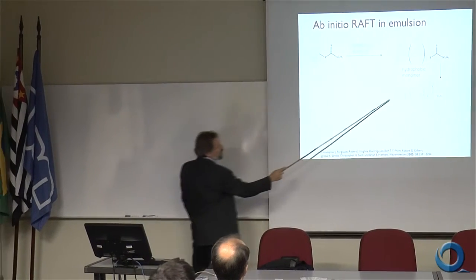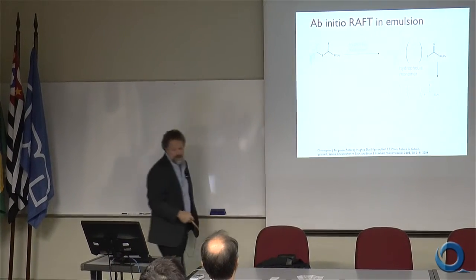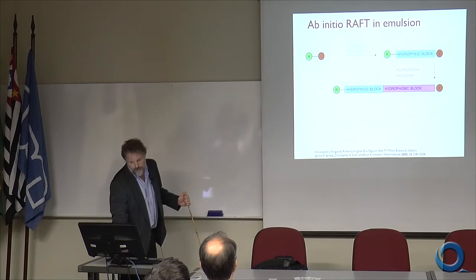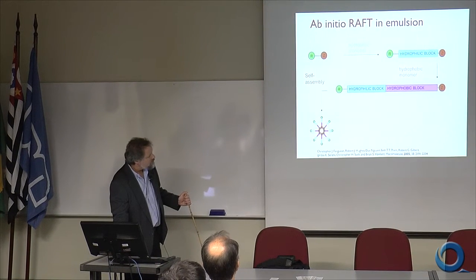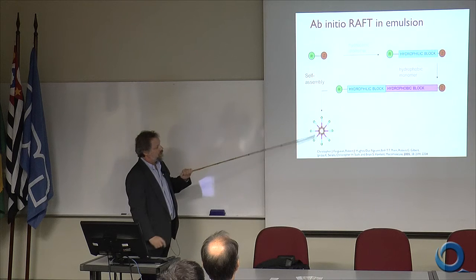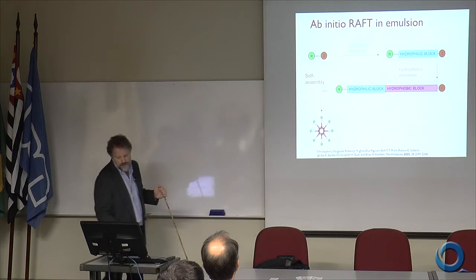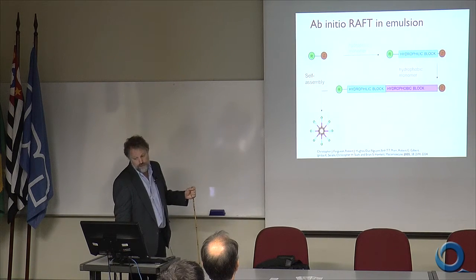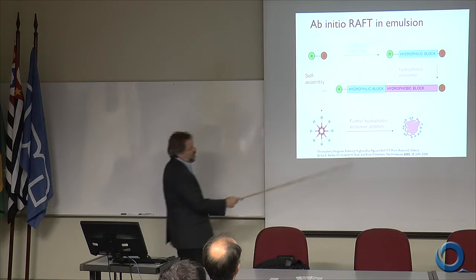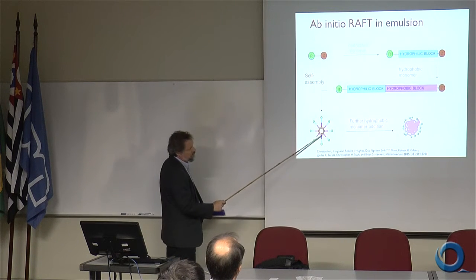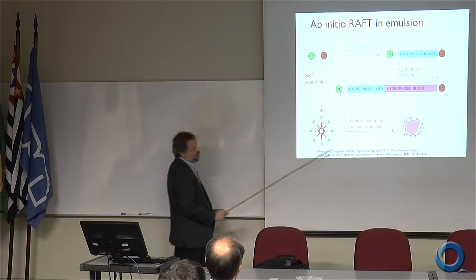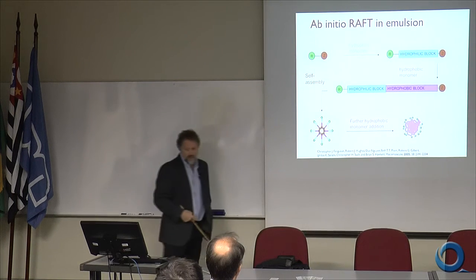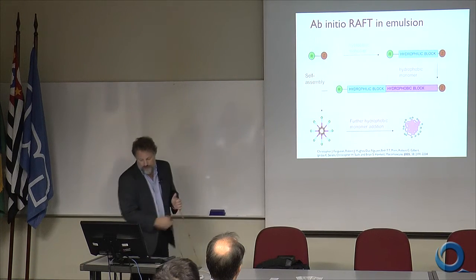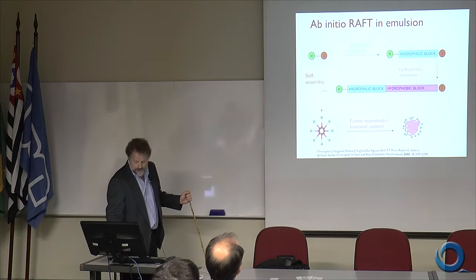So we have our ionic block and our hydrophobic non-ionic block. And as that polymerization takes place, they will start to self-assemble into micelle-like structures. And as the polymerization of the hydrophobic monomer continues, it will take place in the hydrophobic core of this micelle structure, and form stabilized nanoparticles. So that's how we make these nanoparticles.